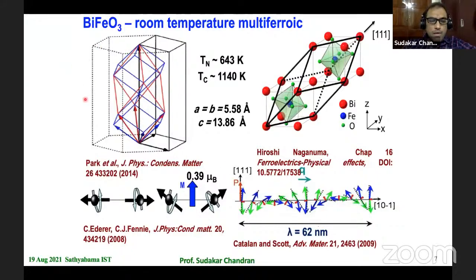I will tell about certain properties, how we control specifically the band gap of this material. And then I'm going to give an application of that in the solar cell, which is an energy conversion device. BiFeO3 is a perovskite structure, like ABO3 structure, but it's not a perfect cube. The one which is shown is a perfect cube, but it's not a perfect cube because the FeO6 octahedra is slightly distorted and tilted, and therefore it does not form a perfect perovskite structure, and therefore it forms a rhombohedral structure. So the BiFeO3 structure is a distorted rhombohedra.